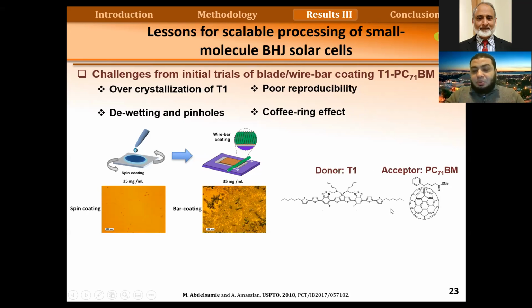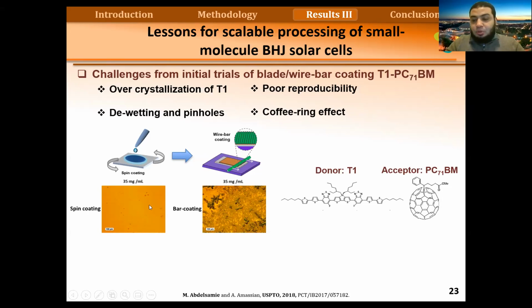So we try to use this with T1 as well, and we used PC71BM as acceptor. In the initial trials, when we do spin coating, we have a uniform film. If we do bar coating, we found the film is non-uniform. We found the formation of very large crystals, and this also leads to the formation of pinholes.